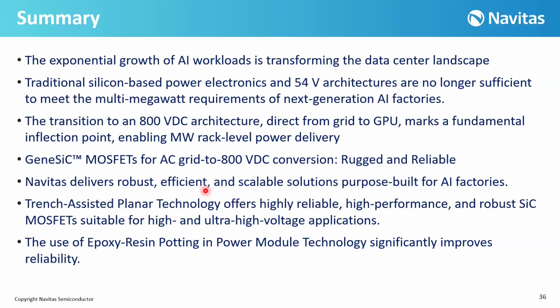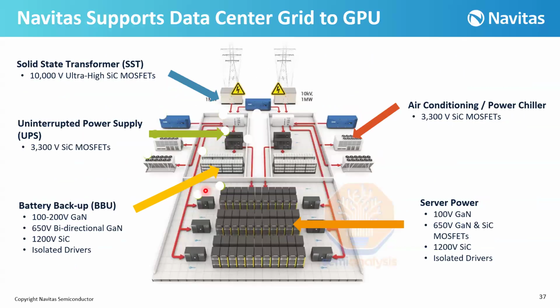And also, I covered the use of epoxy resin in power module technology, which improves the reliability, as I explained in the previous slides, compared with the silicon gel. And once more, Navitas can support the data center grid to GPU with 100 to 200 volt gallium nitride, 650 volt bidirectional gallium nitride, and silicon carbide. We have a wide range from 650 volt up to 10 kilovolt and even higher, which can support different parts of the data centers: SST, UPS, BBU, air conditioning, and server power.